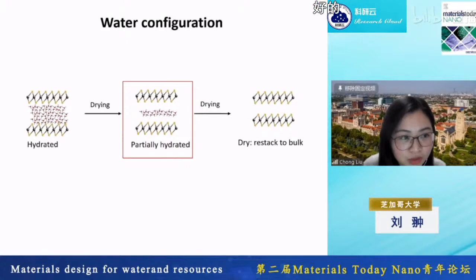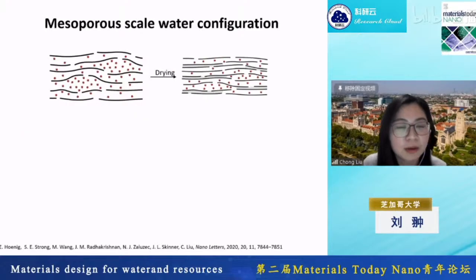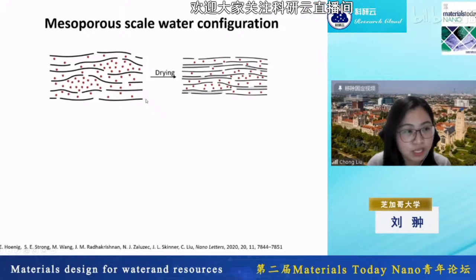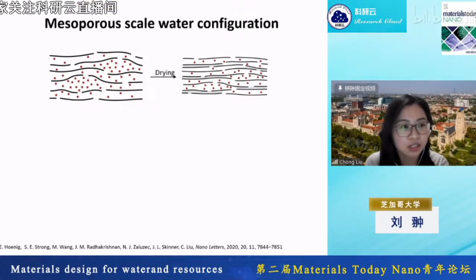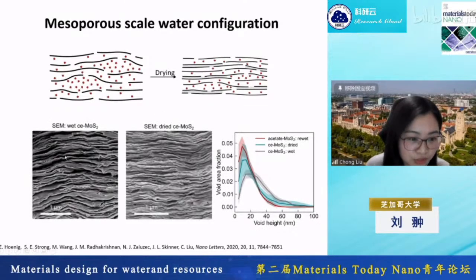If you are talking about one channel, that's fine. If you are talking about millions of channels of identical size or shape, it's fine. But in our case, when the membrane is made, there are a lot of heterogeneities in it, meaning that in a lot of places you have a lot of water and in a lot of places you have less water. And when you are drying something very heterogeneous, these mesoporous scale features don't allow a uniform creation of the 2D channel. You can easily see from this SEM image that you have a lot of these big channels. That will be a point where you lose your selectivity.